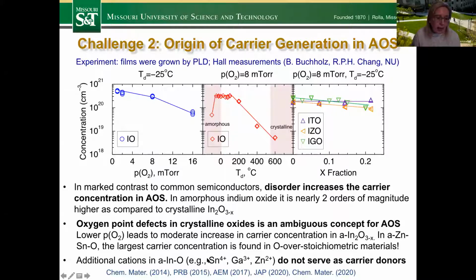Finally, again, unlike many materials, definitely the crystalline materials, when we dope the material in amorphous oxide, we don't see a change in the carrier concentration, very little change. So these additional ions like tin 4+, gallium 3+, zinc 2+, if you put them in the indium oxide, which is 3+, they do not serve as carrier donors, so they don't dope the system. Of course, they affect the properties significantly, and again, I will be talking about it, but they are not dopants in the sense as we used to them in the crystalline materials.